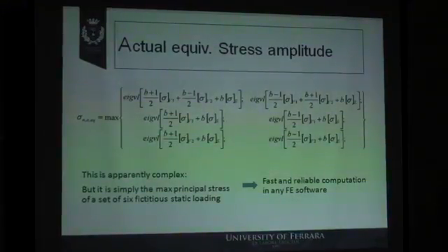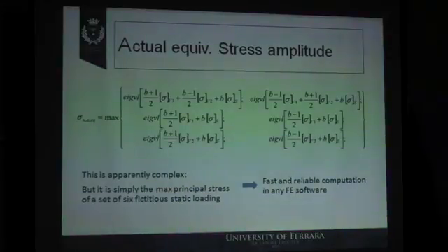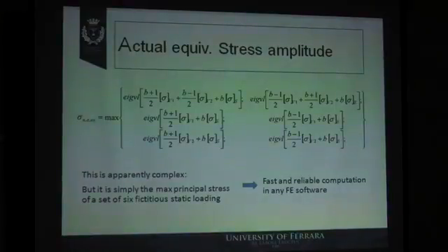I don't know if you agree with me that it's much simpler than it could appear, because, as a matter of fact, with this approach, you can address a fatigue problem with the investigation of 6 fictitious static loadings. That is, these 6 cases.